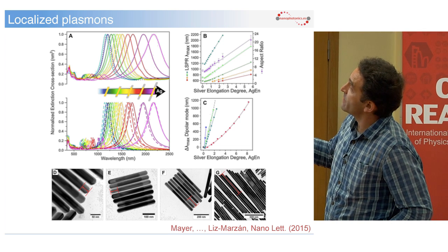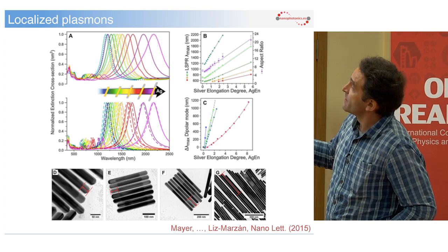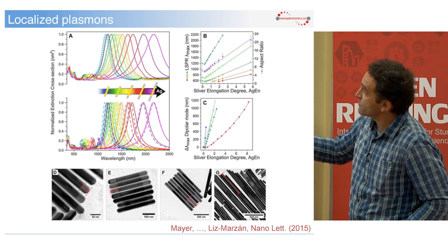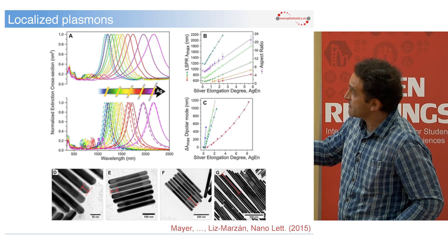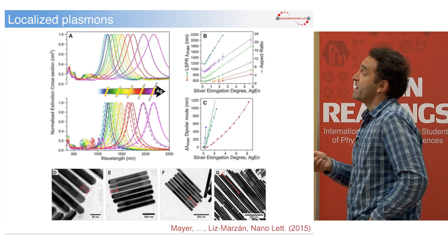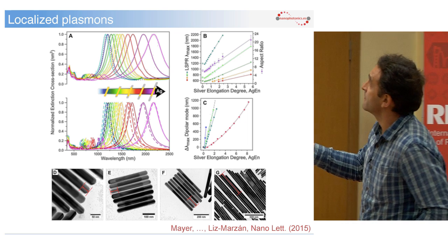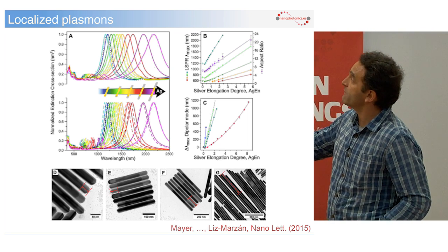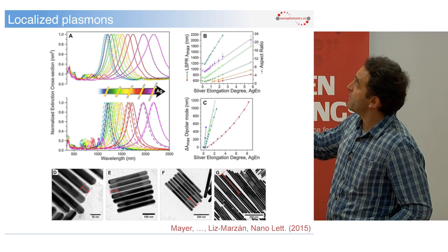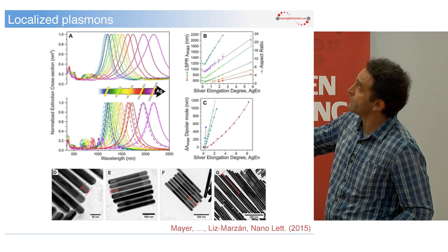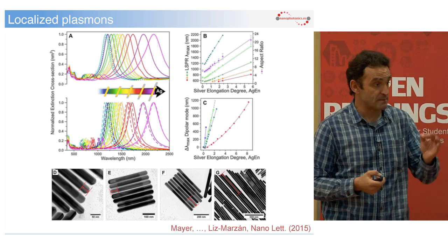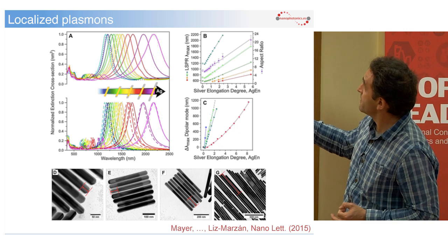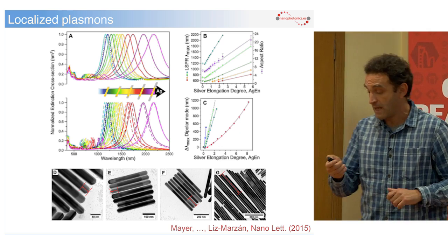One of them is the theory, the other is the experiment. Again, difficult to tell apart. So we basically understand the different modes of these resonances in these nanowires. So this is experiment, this is theory. With electron energy loss spectroscopy, again, you can visualize all of these excitations, dipolar, quadrupolar, etc., all of them. Okay, so these plasmonic modes, with a resolution that is, well, the size of these nanowires is 34 nanometers in diameter.